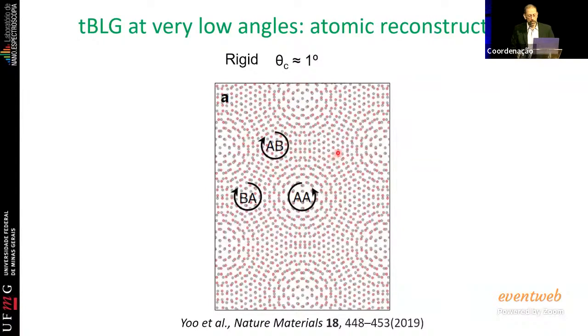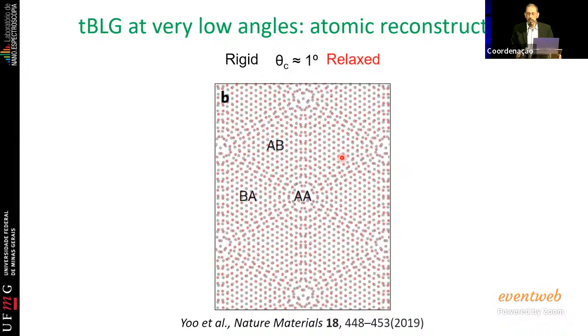And at these very corners is where what I told you before, the stable situation, happens. The atom of the top layer falls exactly in the middle of the hexagon formed by the bottom layer. This is the so-called AB stacking, and this is what is more stable for graphene, for bilayer graphene and for graphite. But what happens when the angle is too small? When the angle is too small, the system is unstable, and the room temperature thermal energy is enough to make the system rotate back and restack in the more stable AB structure.